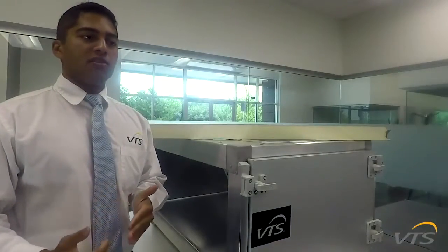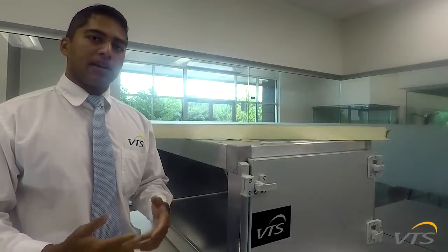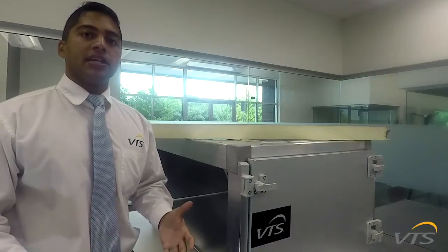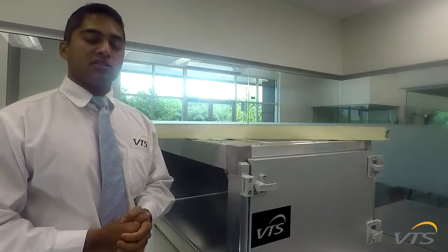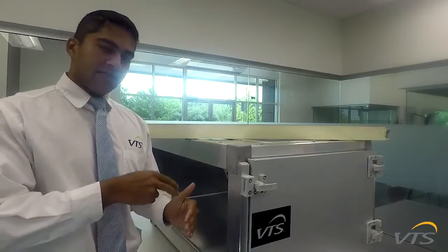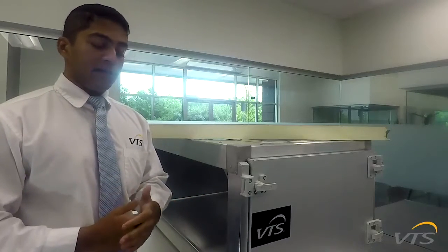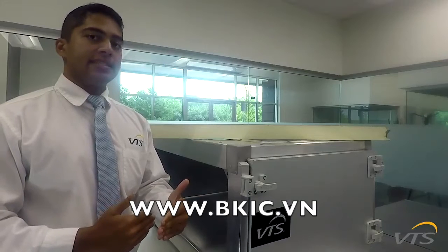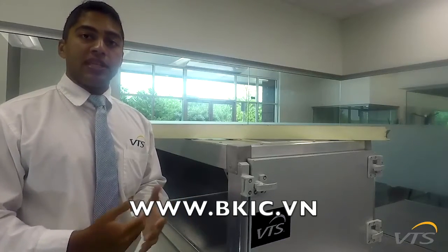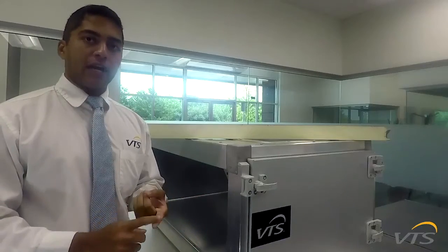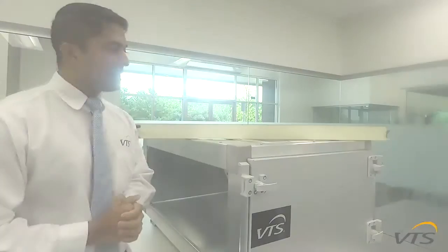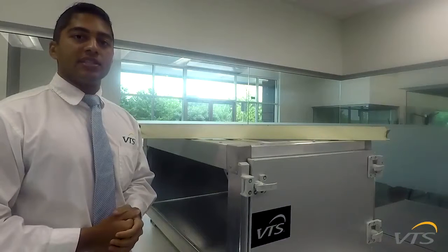So going on those lines, why do those air pockets and those bubbles occur? Typically it's because of the manufacturing process. So you have your flat panel, the foam gets sprayed in there, and it rapidly grows to almost instantaneously fill that void. Now if that foam settles before the air escapes, that's where you get your air pockets and your bubbles forming within the casing. So how do we avoid that situation?